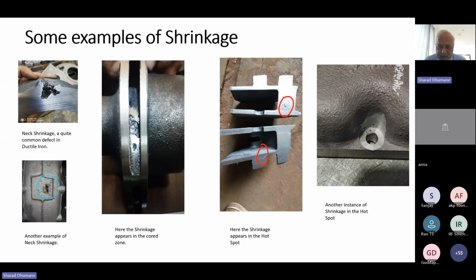Here, I would like to mention this briefly, that in one foundry, we struggled with defects in one particular cylinder head for a very long time, took many iterations, many trials, and our customer was facing heavy rejection after machining because these defects were revealed only after machining and during pressure test. And since it was happening in a bore, we thought that it was a shrinkage, and we were taking action on shrinkage, and it really didn't respond.